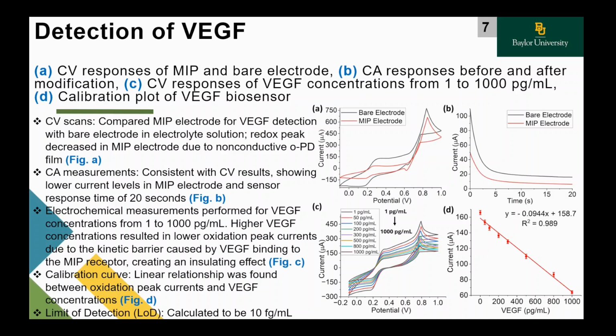Figure C shows that the higher VEGF concentration resulting in lower oxidation peak current due to the kinetic barrier caused by VEGF binding to the MIP receptor, creating the insulating effect. In the calibration curve at figure D, linear relationship was found between oxidation peak current and VEGF concentration, and the limit of detection, LOD, was calculated to be 10 femtogram per milliliter.